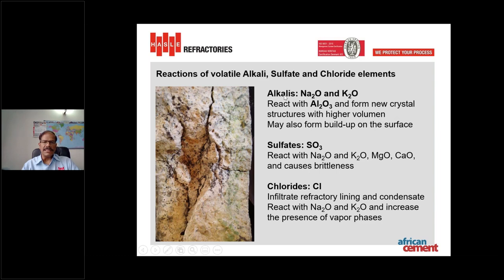So what happens? These alkalis react with the alumina of the refractories and form a new crystal structure with high volume, which cracks the refractory lining, and it also forms a buildup on the surface of the refractory. And sulfates react with the alkalis, that is Na2O, K2O, MgO, and CaO, and cause brittleness in the refractory, and the performance of the refractory reduces. And chlorides infiltrate the refractory lining very easily and condense in the refractory. When they react with the alkalis, they create cracks in the refractories and lead to failure of the lining.